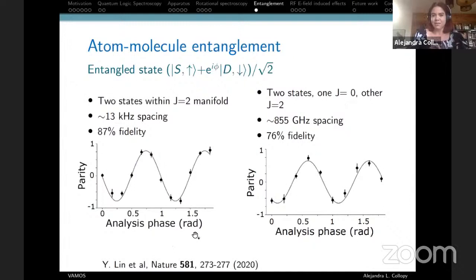As I mentioned, I'm going to shift gears just a little bit here and mention that we can use these quantum logic techniques in order to prepare an entangled state between the atomic ion, so the S and D levels in the calcium, with two states we can label as up and down in the molecular ion. And we performed this with a couple of pairs of up and down states. We've done it for 2 states within a J equals 2 manifold that are spaced by 13 kilohertz, and 2 states in different rotational manifolds that are spaced by 855 gigahertz.